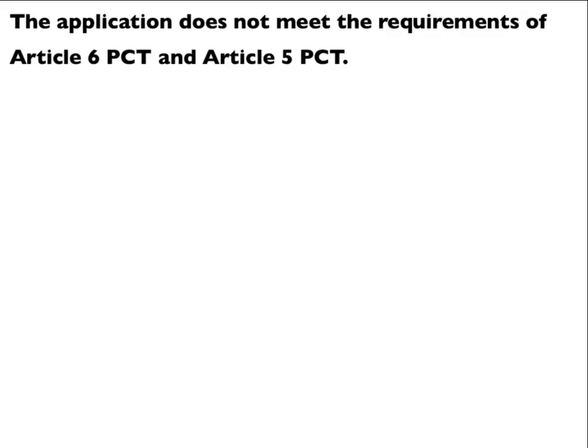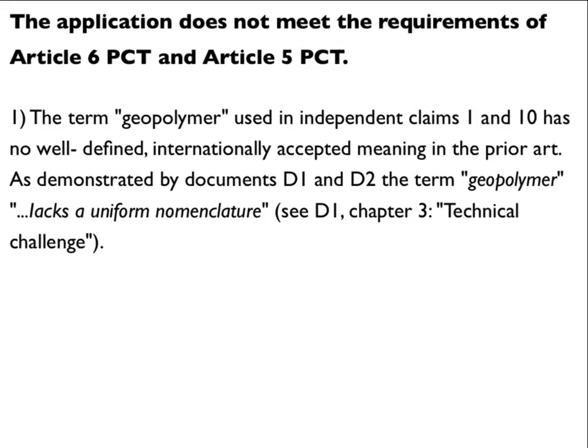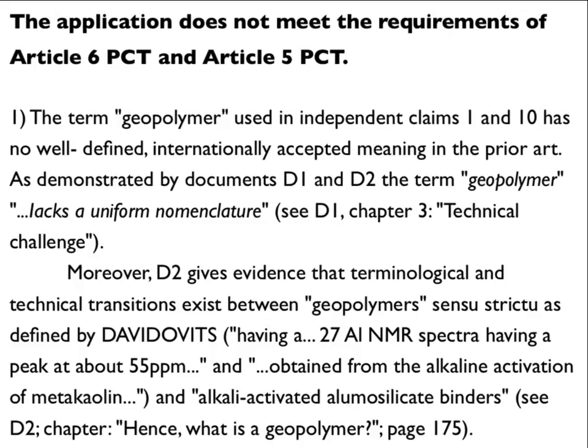And the examiner provides the answer. This application does not meet the requirements of article so and so. What are the consequences? The term geopolymer used in the claims has no well-defined, internationally accepted meaning in the prior art, as demonstrated by documents D1 and D2. The term geopolymer lacks a uniform nomenclature. Moreover, D2 gives evidence that terminological and technical transitions exist between geopolymers sensu stricto, as defined by Davidovits, having 27Al NMR spectra with a peak and so forth, and obtained from the alkaline activation of metakaolin, and so-called alkali activated aluminosilicate binders.